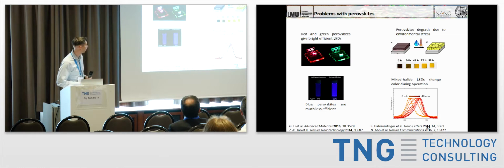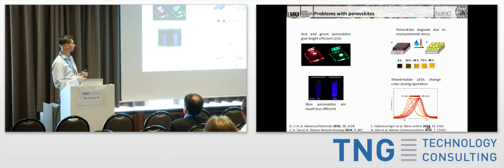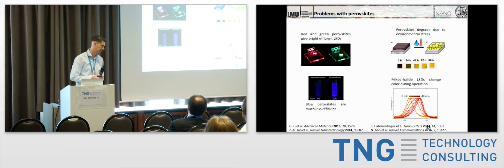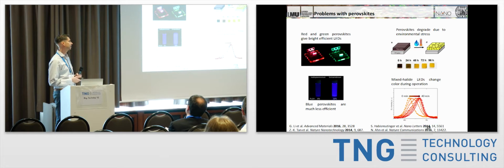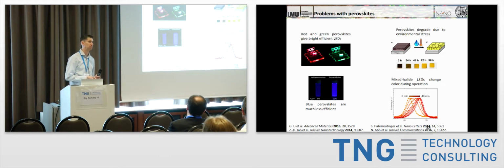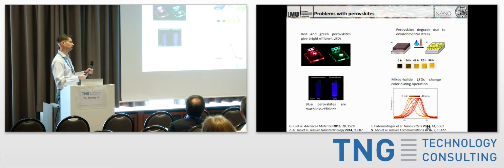Another problem that I'm not going to get into in too much detail is that I told you can mix the halide composition quite nicely to get individual emission colors in there. And one of the problems, though, is that despite the perovskite being more or less semiconductor-like and having a nice crystal structure, these ions don't actually like to sit necessarily at the same spot that they're put in. So if you put on an electric field, which you need quite large in LEDs, a couple of volts in there, what happens is that these ions then start to migrate, to go to different areas.